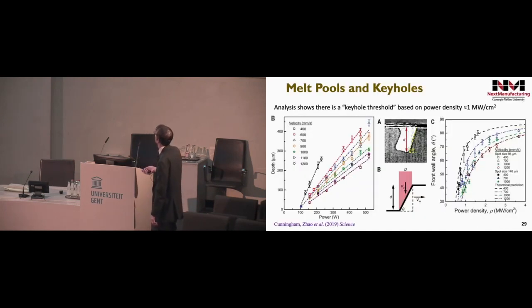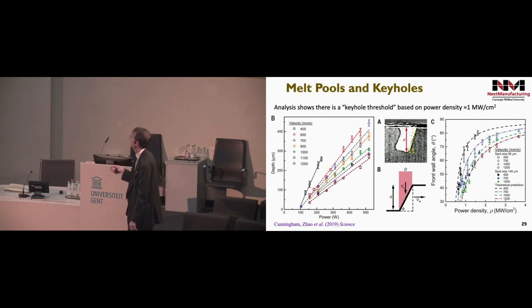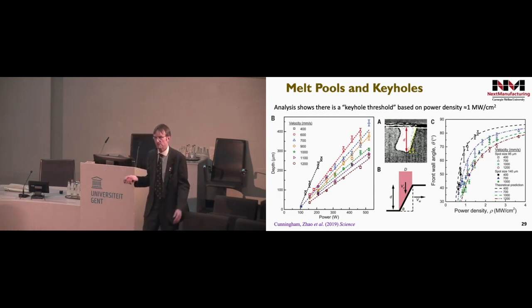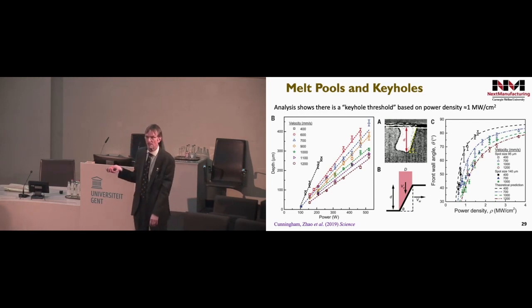Okay, so moving right along. I won't try to explain all of this, but briefly, what we discovered pretty quickly is that the keyhole depth was linear in the power, but if you trace back all of these lines, you find that they converge on a common point, a common intercept, and that point represents a threshold value of power. As you might imagine, that threshold depends on the spot size. So this was where we quickly discovered that power and speed are very important, but if you're going to try to avoid keyholing and keyhole porosity, you have to pay attention to power density, which was not particularly obvious to people. And so that was already an interesting finding.